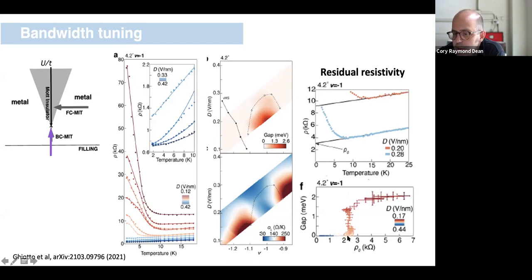And that transition point is the same transition point where we induce the existence or non-existence of the Mott gap. So this regime here is basically defining where there is the Mott gap. This regime is defining where there is not the Mott gap. So there's really a kind of abrupt step in this residual resistivity. What this precisely means, we're not exactly sure.